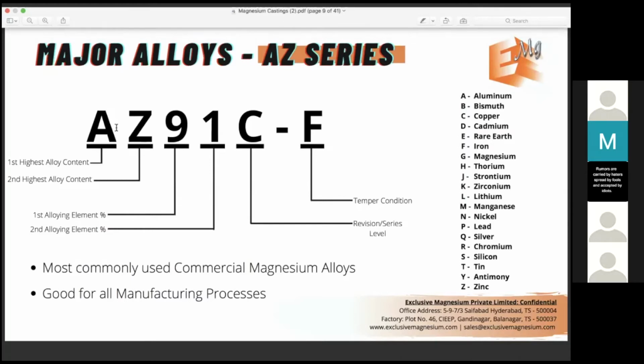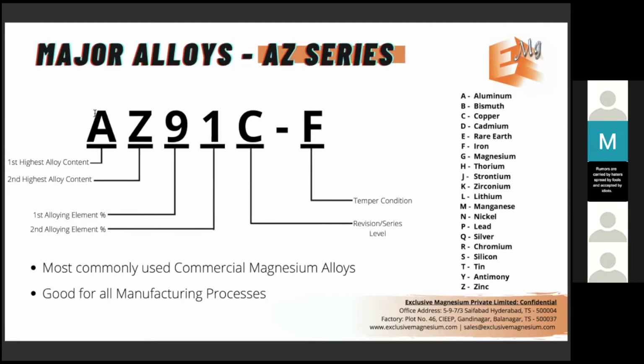So as you can see from this presentation, this is the AZ series, where A stands for the highest alloy content in this alloy, right? Here on the right side, you will see a chart, a list of names of the alloying elements that can be used in magnesium. You can use that to decipher what A means, what Z means. That's aluminum and zinc. The 9 and the 1 stand for the highest. The first number stands for the percentage of aluminum, the highest alloy content element. So that's 9% aluminum and 1% zinc.